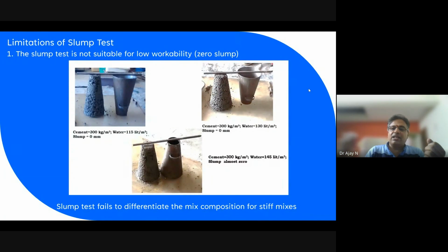When we add extra water, 130, 145, then scientifically, when we introduce water, it automatically reduces some frictional force. When the frictional force between particles or aggregates reduces, the slump value should go up. But in this case, what happens? The lower workability mix is still showing 0. So it clearly says the slump test fails to differentiate among the mixes, because we have 3 different mixes, but the slump value is the same, 0.